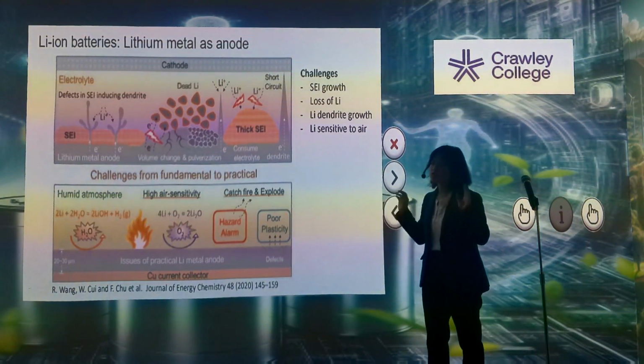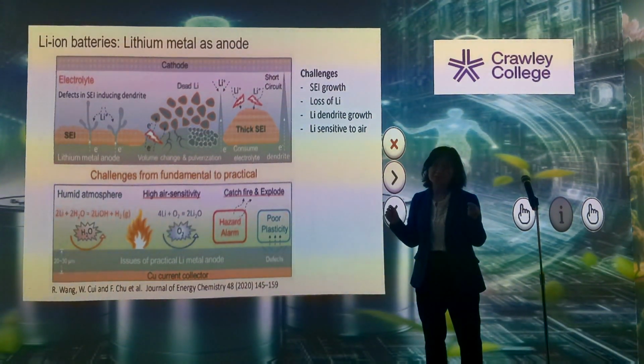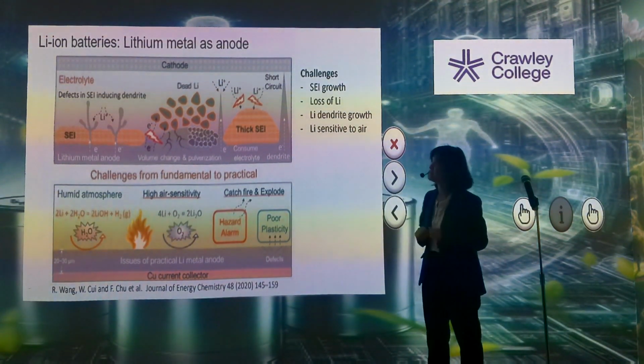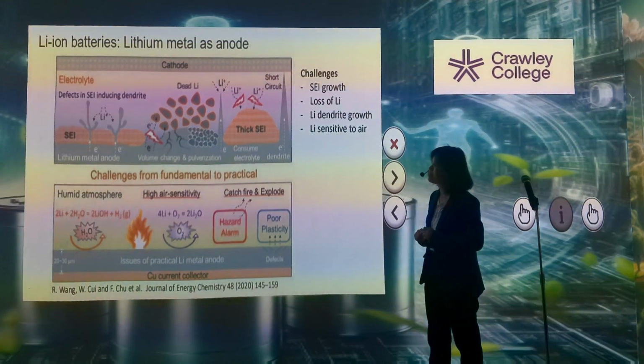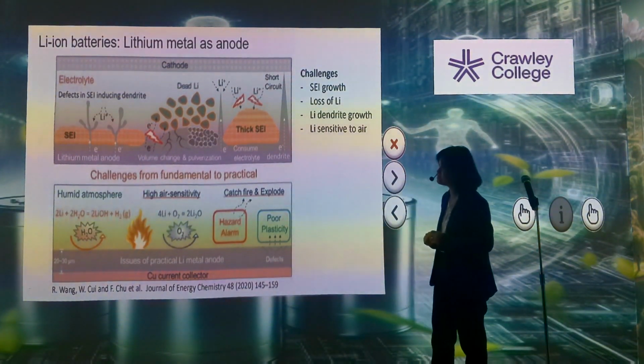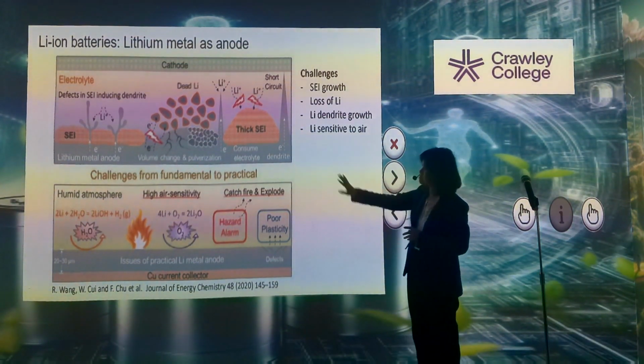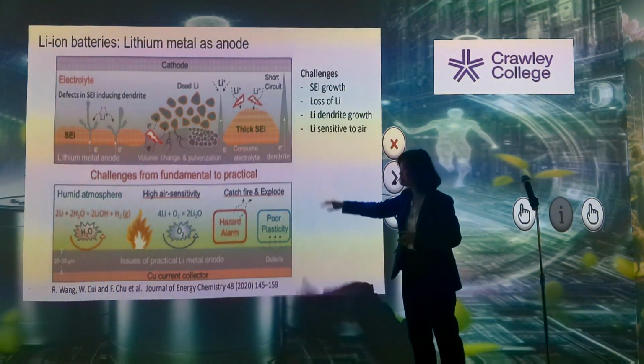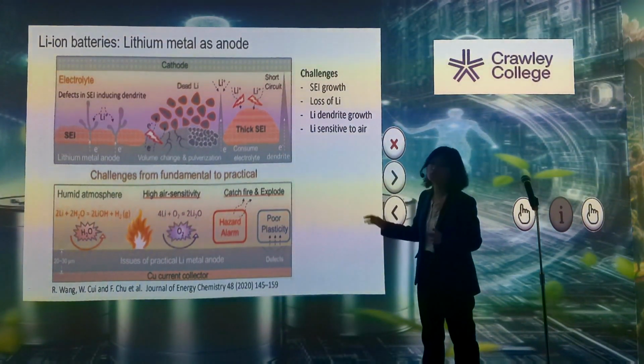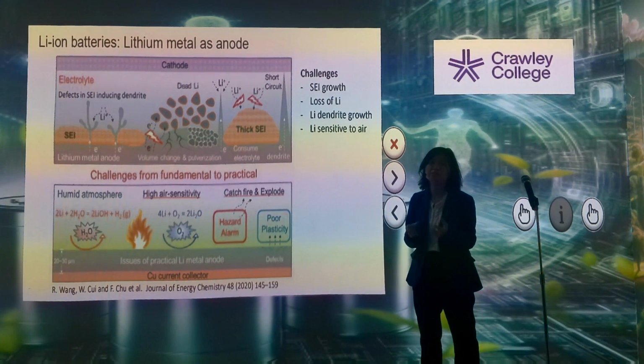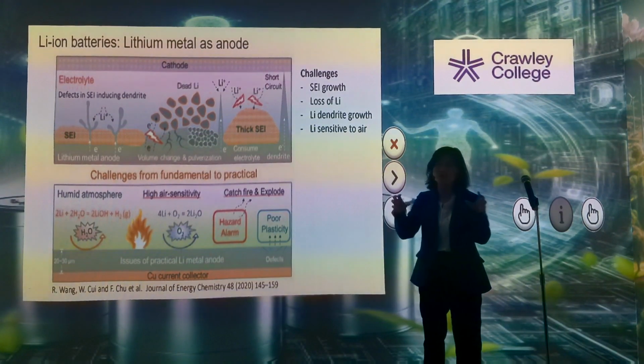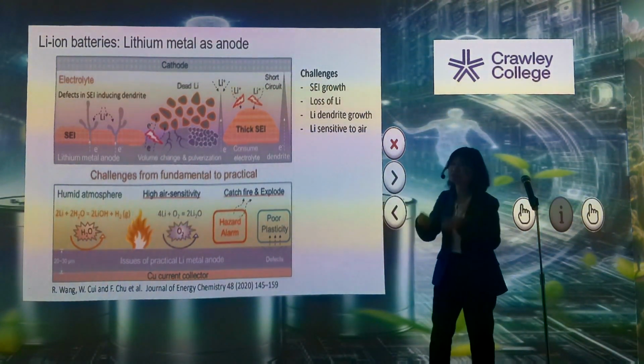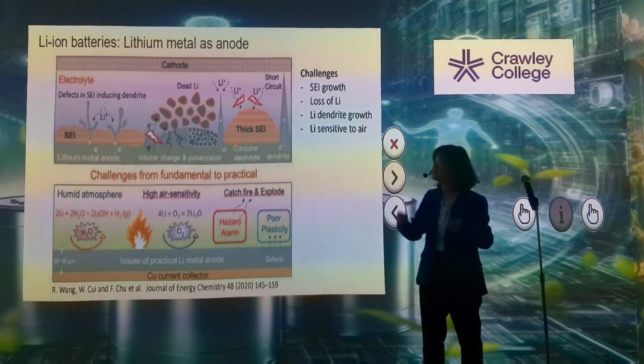Of course, the ultimate choice for anode would be lithium metal, because it has the highest theoretical storage capacity and the lowest potential. That's the ideal anode we want. However, it comes with a lot of challenges because lithium metal is very reactive. It can react with the oxygen and moisture in the air, and therefore you have to handle it very carefully in vacuum conditions. And it's not very easy to create that kind of vacuum condition. So we have a glove box in our lab, but you can only make batteries on a very small scale.